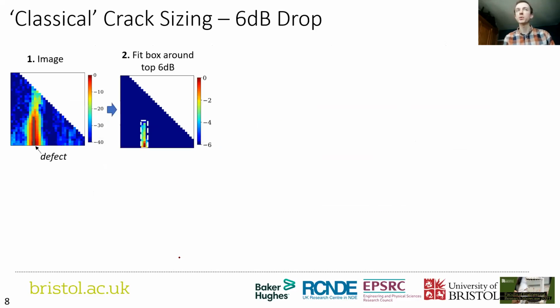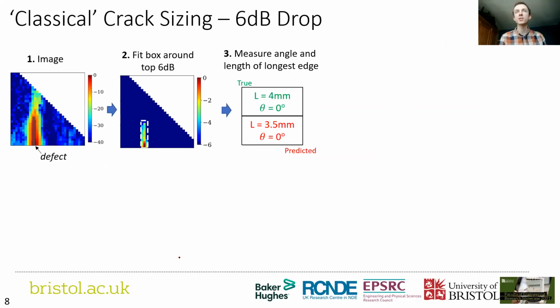You fit a box around the top 6 decibels of that image, and then you just measure the angle and length of the longest edge. And sometimes it works really well, but it does rely on the fact that the indication is the same shape as the defect. That's not always true.